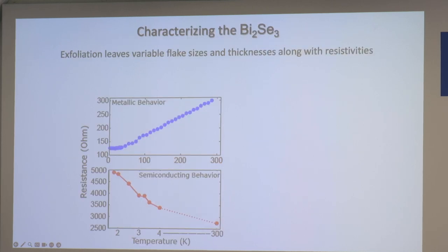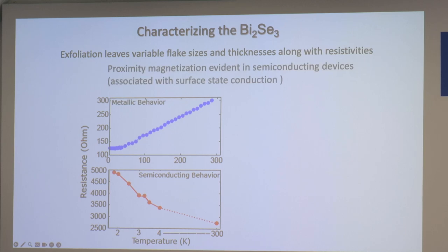We also characterized the bismuth selenide. This is the other problem. When you're dealing with flakes, it's nice because you get clean samples that you can couple to things, but you also get what you get. And so we tried again to have pretty thin samples, but when we measured them, we sometimes saw different sorts of behavior. Again, we can't control exactly where the Fermi energy is in these systems. We just have to try the ones that seem to have the Fermi energy closest to within the gap. In this case, we found that some samples showed metallic behavior consistent with surface states, and some showed semiconducting behavior consistent with the bulk freezing out at low temperatures.